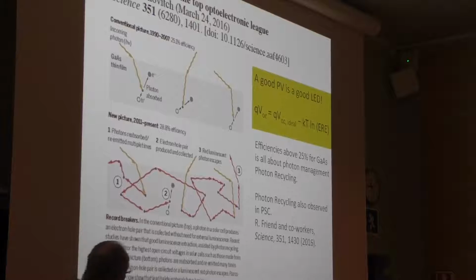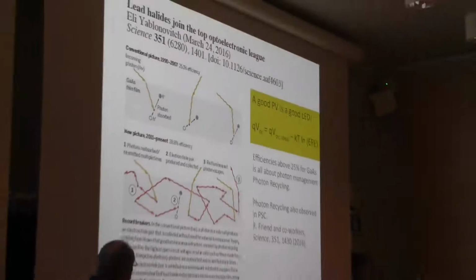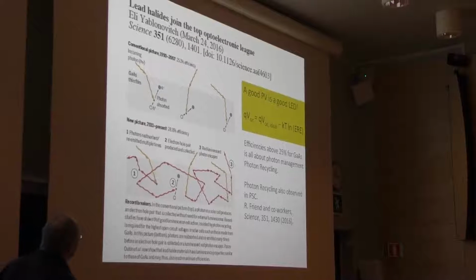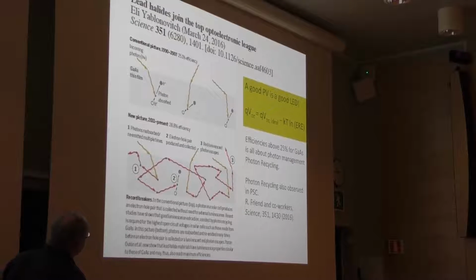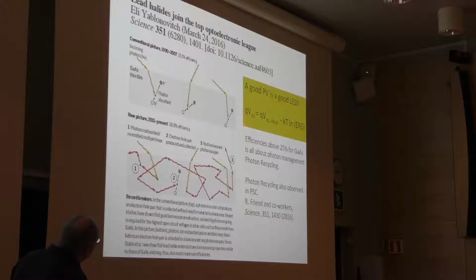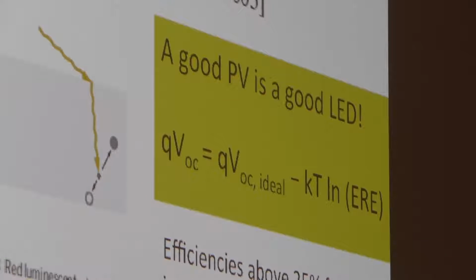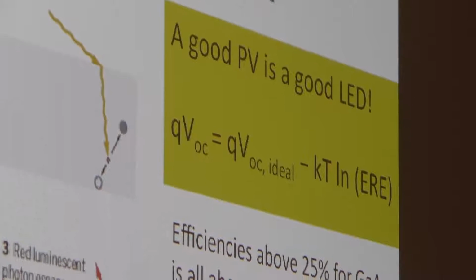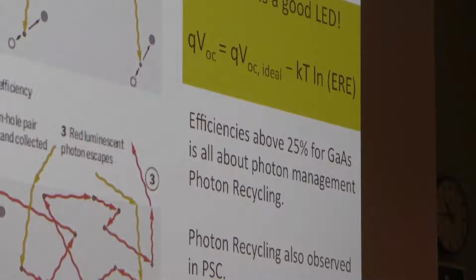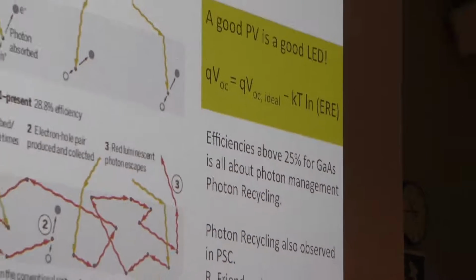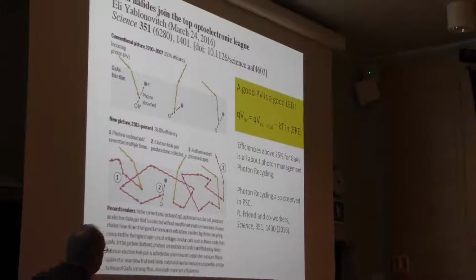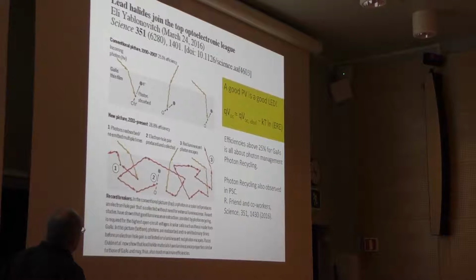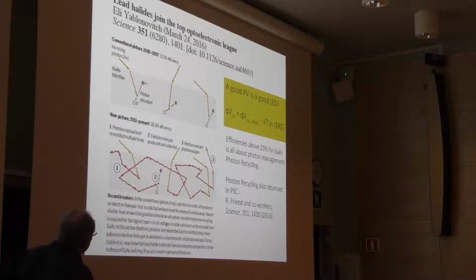So I'm coming to the end, and that is to see how far can we go. There is a mechanism for gallium arsenide, the best solar cells I said, and they lose very little VOC. Here is the theoretical Shockley-Queisser equation. The VOC you get is the theoretical minus the loss from external luminescence. So a good solar cell with good VOC should also be a good LED. So the recombination should be radiative, then it's an efficient solar cell. If you go to high VOC and you have luminescence, radiative recombination, that's good quality. So VOC goes together with the electroluminescence. And gallium arsenide has high values here.